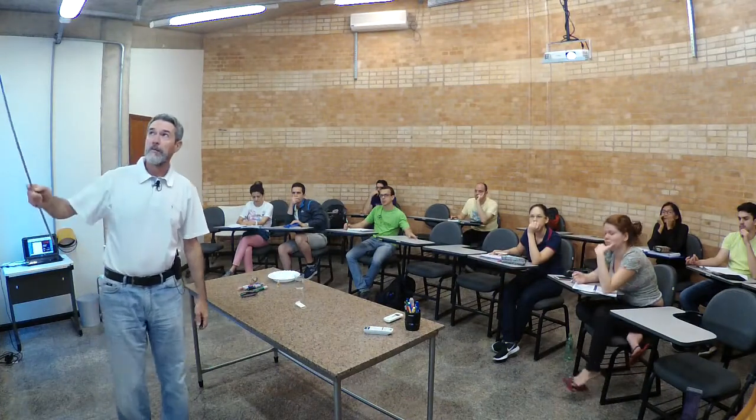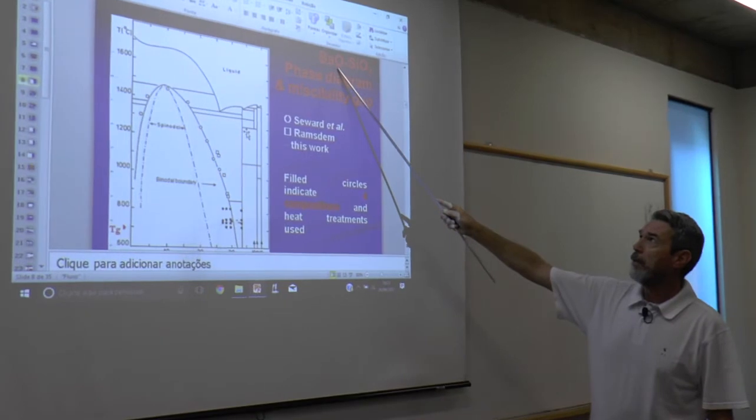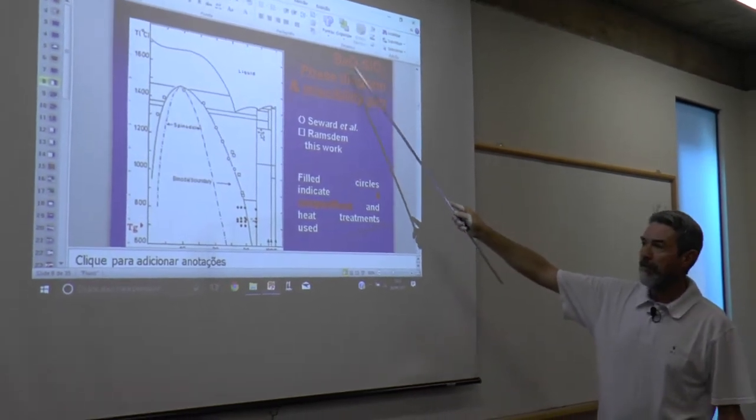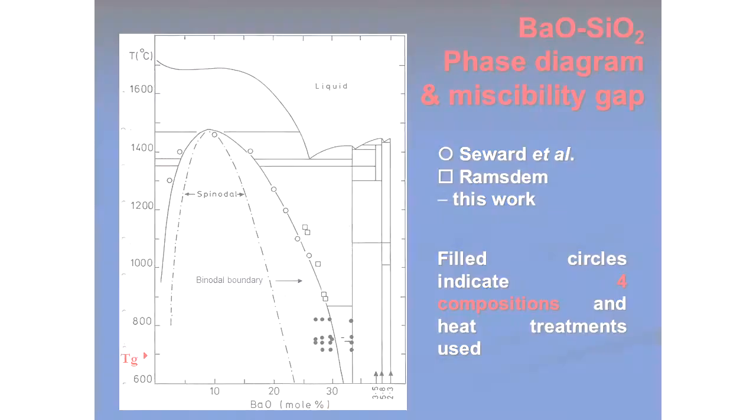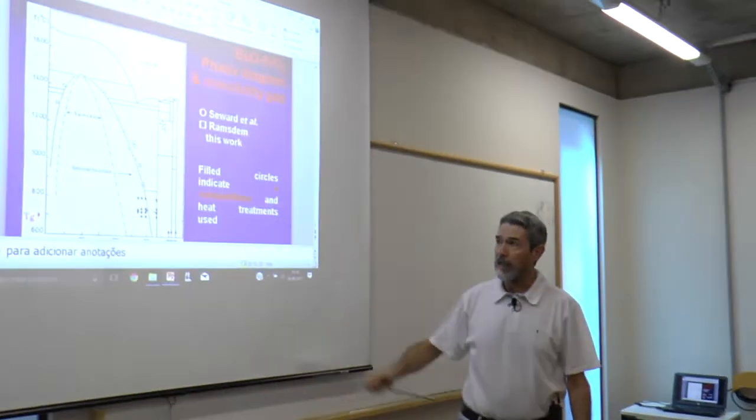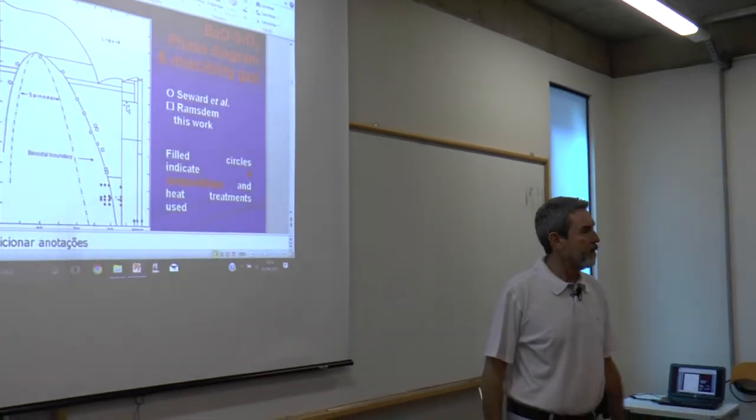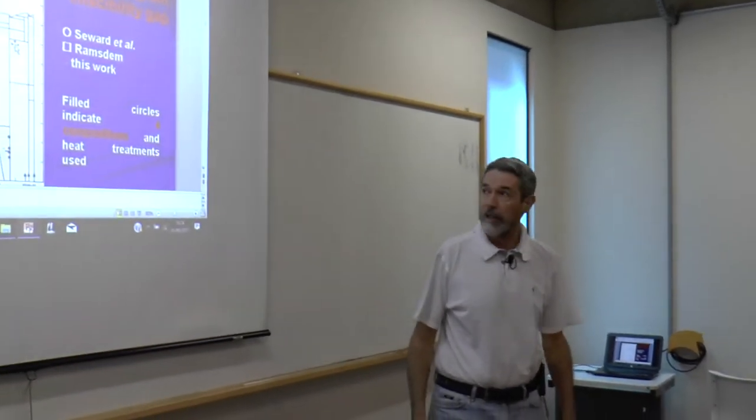This is one example. Barium silicate is a very good example because barium is a very heavy atom. So to look for these nanostructures in an electron microscope is very advantageous if one phase has a much higher electronic density than the other. So to look either with electron microscopy or small angle X-ray scattering, the barium silicates are good model systems to understand the liquid phase separation.